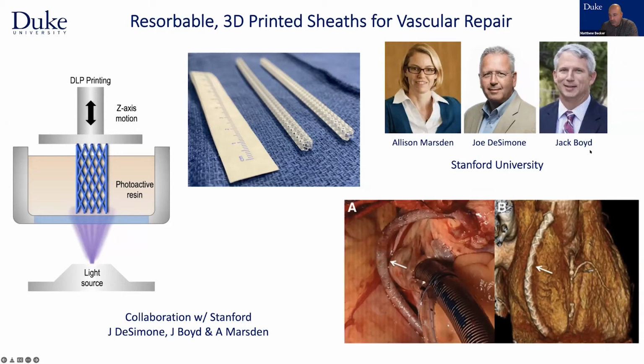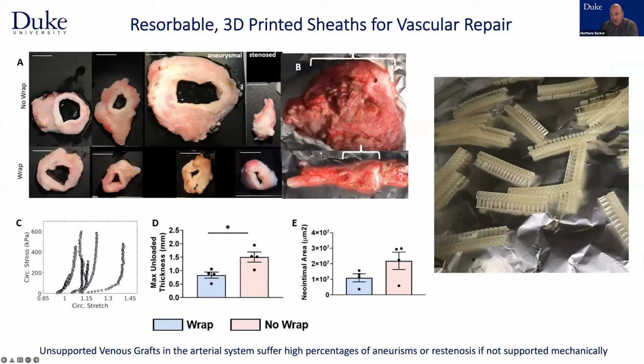And so Jack Boyd, who's probably one of the best surgeons in the country, has come up with a sheath. This is a 3D printed sheath that goes around the outside of the vein, designed to support it mechanically for 4 to 6 weeks and then degrade over 12 weeks. And during that time, the vascular system is able to begin to remodel. And the clinical outcomes, at least in their sheep and rabbit models, are quite promising. And so what you see here on the right are the 3D printed sheaths. They have the design support structure here.